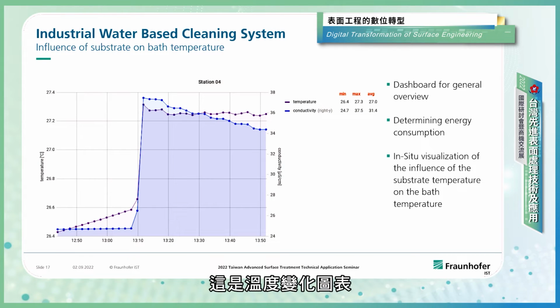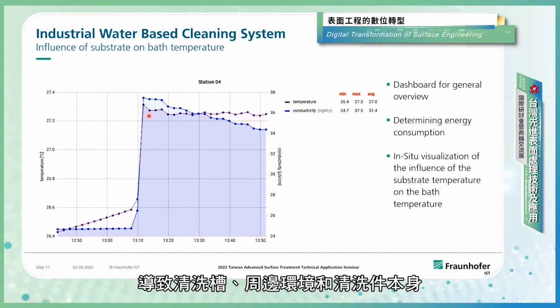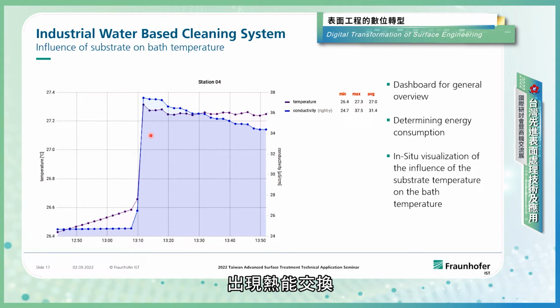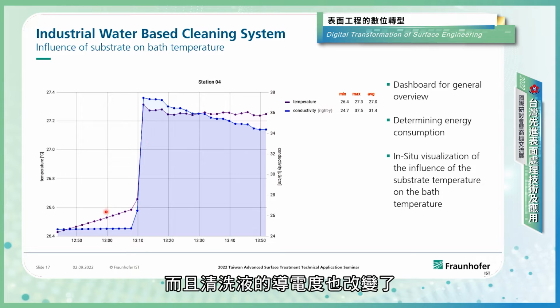Here you can see the temperature change when we enter with a massive part which is warm into a bath. We can see when we are entering the bath that we increase the temperature. There's a jump in the temperature because the part is heating up the bath to some extent, exchanging the temperature between the bath, the surrounding environment, and the part itself. And also it's influencing the conductivity of our cleaning solution itself.